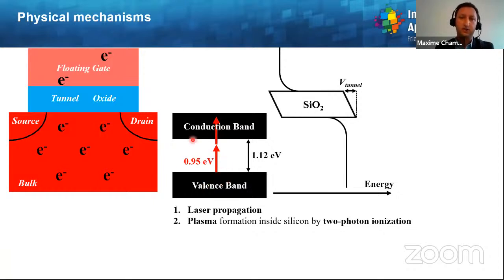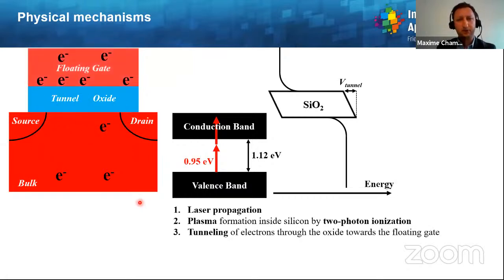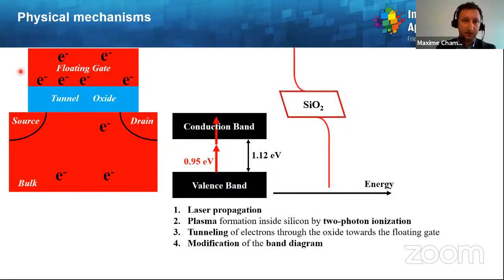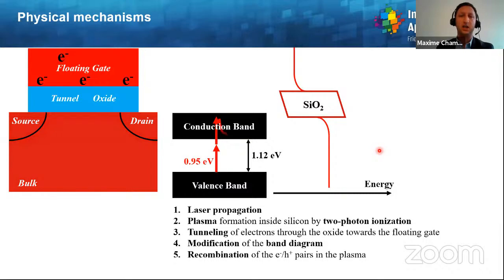Here is represented the two-photon absorption. Then some electrons will be able to tunnel through the oxide layer toward the floating gate. Then this increase in the negative charge will lead to a change in the band diagram. And finally, the electron and hole pairs that have been produced in the silicon substrate will recombine,